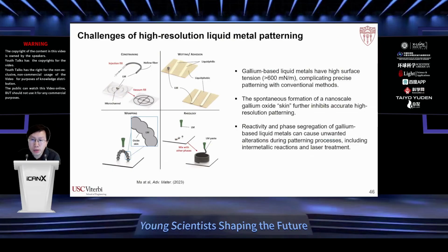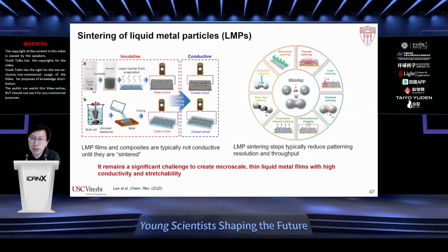So to mitigate this surface tension issue of bulk liquid metal, people have developed different methods to sinter or join individual microparticles, or liquid metal particles, LMPs. Individual LMPs are particles, so surface tension is less of an issue, but they are not really conductive because of the insulating oxide shell. So people have developed different types of sintering techniques to join them together. But these processes reduce the patterning resolution. So it remains a significant challenge to pattern liquid metal at micro scale, both in terms of line width and thickness.